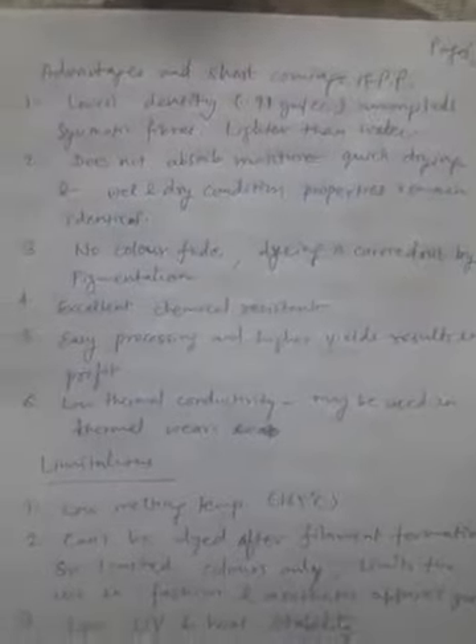Now on the basis of their functional properties, we can list polypropylene advantages and shortcomings here. You can see that because of its lowest density, it is the lightest among all synthetic fibers, even lighter than polyethylene and lighter than water. Its density is 0.91 gram per cc, and it does not absorb moisture quickly, so you get a quick drying property. Yes, and also because of hydrophobicity, or you can say 0% moisture regain, in both wet condition and dry condition the properties of the fibers remain identical before and after wetting.